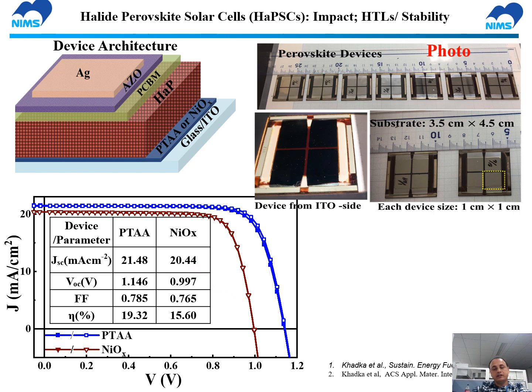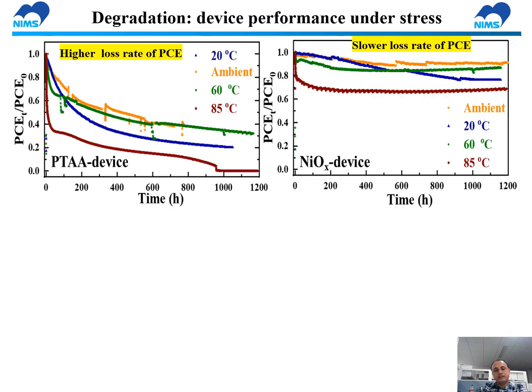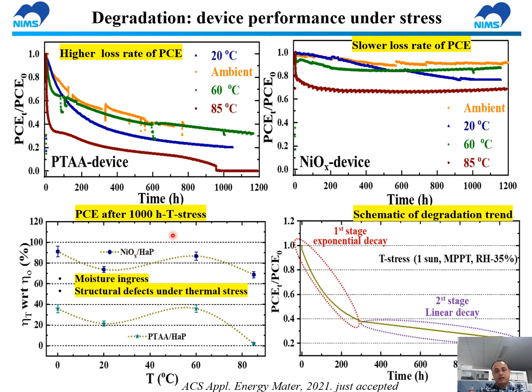We use those devices for the device degradation analysis, and we place those devices under different thermal stress. By looking at the device efficiency trend under different thermal stress, we can see the device with nickel oxide has much better device stability compared to PTAA. If we see device efficiency after 1000 hour thermal stress, there is some variation. However, if we compare the device degradation trend, we can notice two stages of device degradation: this one is exponential decay, and later it follows the linear decay.